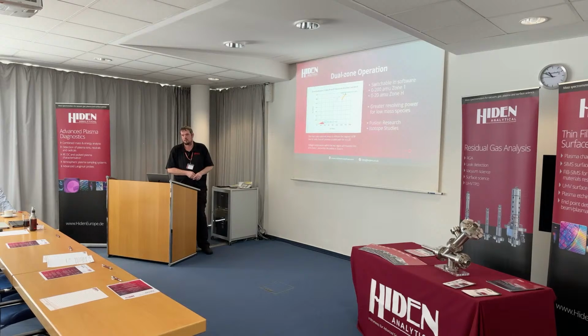So it's not like the mass spectra is dependent on the mass numbers, and sensitivity is different for different mass numbers? Because if that is the case, it would be hard to compare the relative quantity of the gases. Yes, if you wanted to do some measurements in zone H and some in zone 1, you would have to calibrate between the two. Perhaps do an RGA measurement with the internal ionization source, or with the plasma in a steady state, make one measurement with zone 1 and one with zone H, and then you can work out the correction ratio between the two.